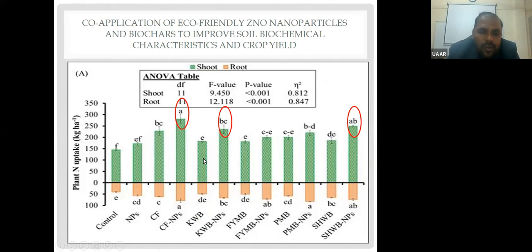This is sole, and when kitchen waste biochar combined with the nanoparticle, only 10 milligram of zinc oxide nanoparticle was applied, and this is a sole, and it is combined with the nanoparticle. So when nanoparticle was applied as an additive with these fertilizers, they increase plant nitrogen uptake up to 20 to 30%, and also the yield of Rhodes grass.